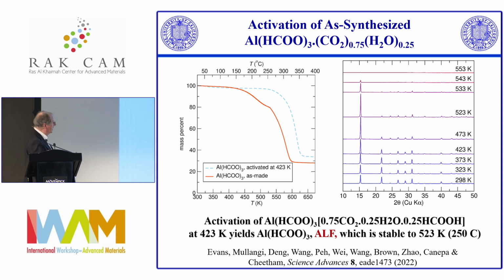So Dinesh Mullangi, who worked with me in Singapore, was able to activate the aluminum formate. And I'm still amazed that nobody had ever looked at this thing over the last 15 or 16 years, but you can activate it without destroying the structure. And so these are the temperature-dependent powder patterns. As it loses the CO2, and there's a bit of other stuff in the cavities in the as-made material, you get the pristine aluminum formate with nothing in the cavities. And we call that pristine material ALF for simplicity. And ALF is very stable. So in the TGA, once you've activated it, it's stable up to about 250 degrees in air. So it's a very stable material.